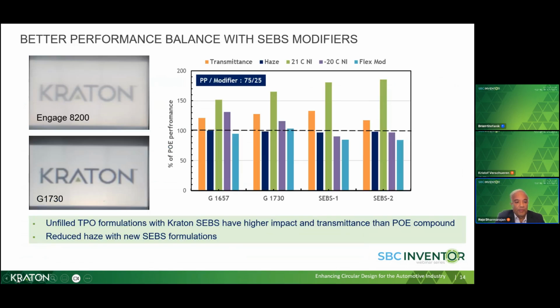So in this study, we are showing a series of unfilled TPO formulations in which the polypropylene matrix is the homopolymer 20 MFR with a 25% impact modifier. So we are comparing the performance of our commercial Kraton polymers G1657, G1730, and 2 new grades, SEBS1 and SEBS2, with a polyolefin elastomer, which is Engage 8200, a product from Dow Chemical. So we are plotting the performance relative to the performance of the POE. So the horizontal line that you see there at the 100% is the performance of POE, and we are comparing how each of these modifiers compare with that of POE.